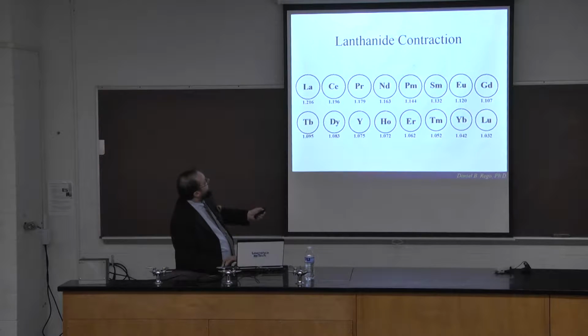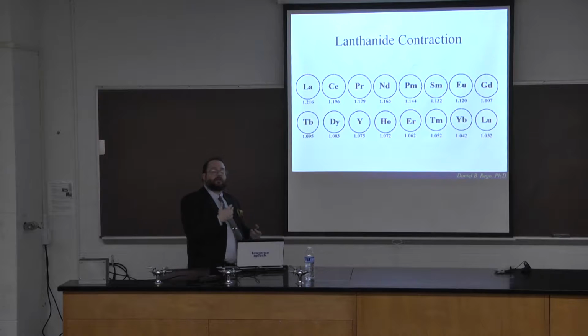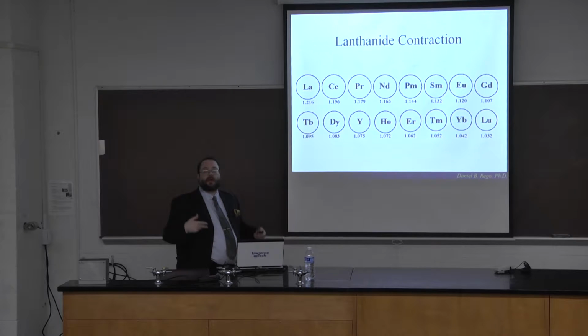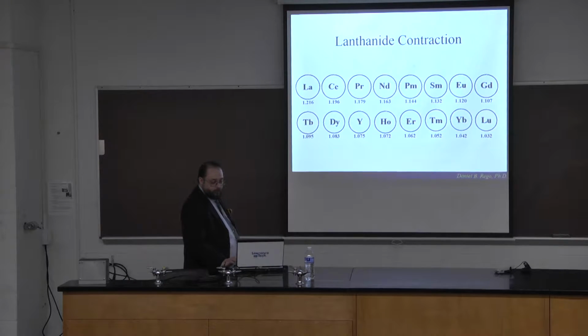Which means that the lanthanide contraction plays a key importance in the chemistry of the lanthanides. So as you go along the series, lanthanum, cerium, praseodymium, and so on to lutetium, I also included yttrium here. This is actually a d element, but it's 3+ and similar in size to holmium, and it's often just treated as another rare earth or lanthanide element for all intents and purposes. But because of this contraction, you have a very gradual and very regular decrease in the ionic radii. And this can have an effect on reactivity.